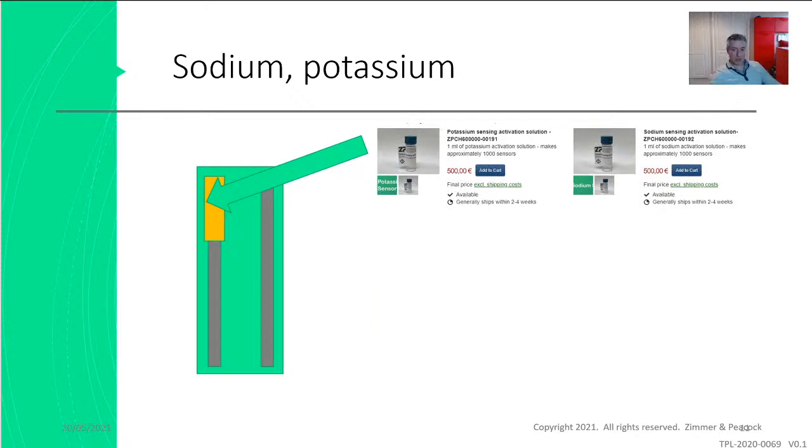Yeah, it's an interesting question. I think we have actually tried. The thing about this kind of setup is you've got gold as your working electrode, and you've probably got silver chloride as your reference electrode. So that means you've got two different or dissimilar metals together, and then you put a solution on them. So when you've got two dissimilar metals in wet contact with each other, you've generally set up a battery, because most batteries are based on the idea of two metals of different reactivity in contact by an electrolyte. So you've generally set up a battery.